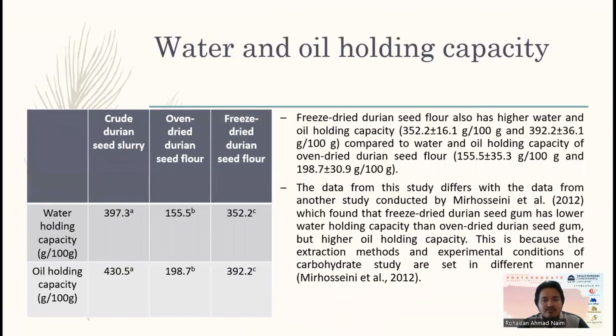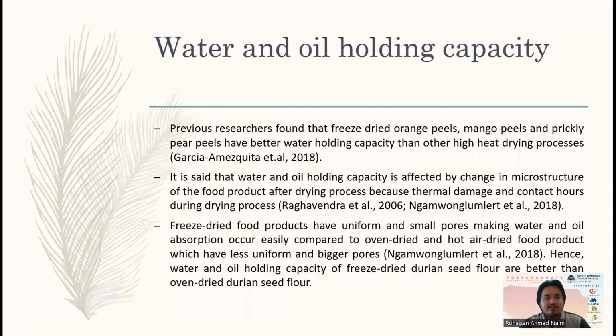Freeze-dried durian seed flour has higher water and oil holding capacity compared to oven-dried durian seed flour. The data differs from another study, which found that freeze-dried durian seed gum has lower water holding capacity than oven-dried durian seed gum, but higher oil holding capacity. This is due to different extraction methods and different experimental conditions of the carbohydrate study.